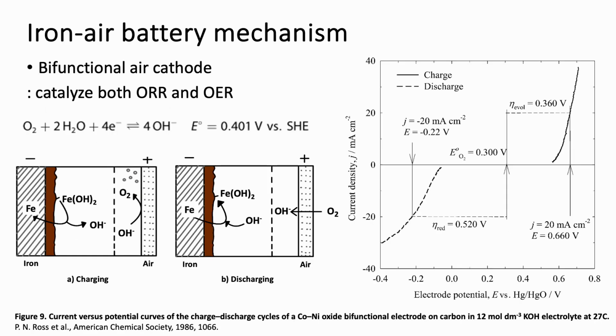The reaction at the air cathode evolves oxygen from hydroxide and water during recharge. Therefore, for an iron air battery, the air electrode must be bifunctional. That is, catalyze both the oxygen reduction reaction and the oxygen evolution reaction. Oxygen reduction reaction includes a multi-step process, so it's notoriously slow. Therefore, one of the key factors in the development of the air-positive electrode has been the selection of the catalyst.